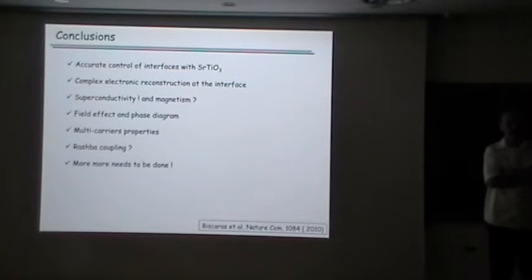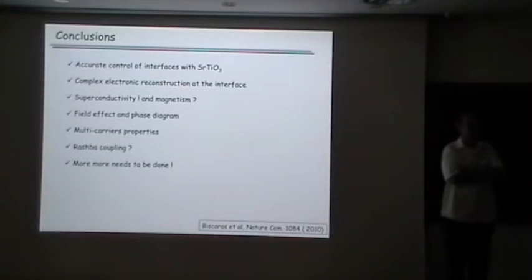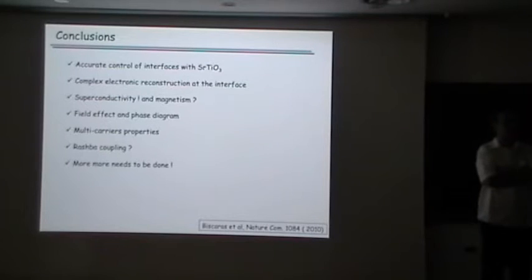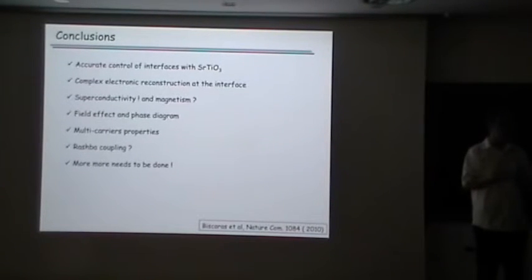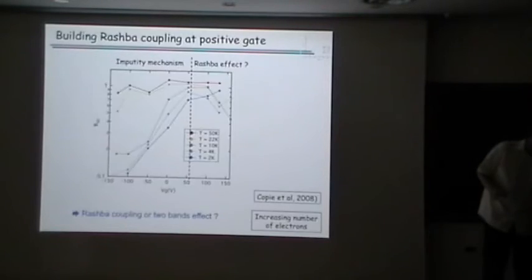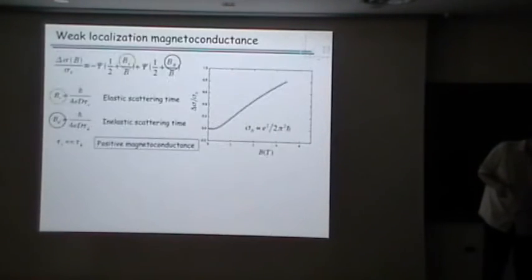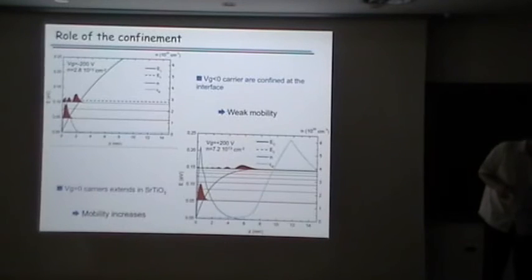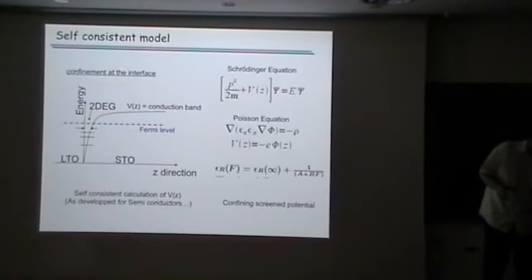When I put the gate voltage, we have different samples. I don't think the density is exactly the good number, because we have studied up to 4 or 5 samples, and the carrier density is not always the same. But what we observe with the gate voltage is always changing rather strongly around 0.